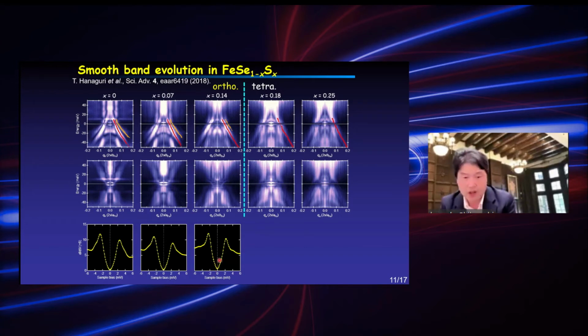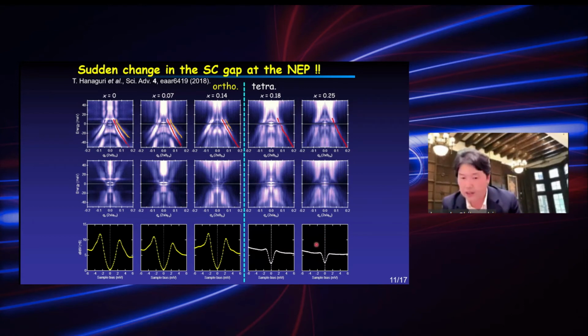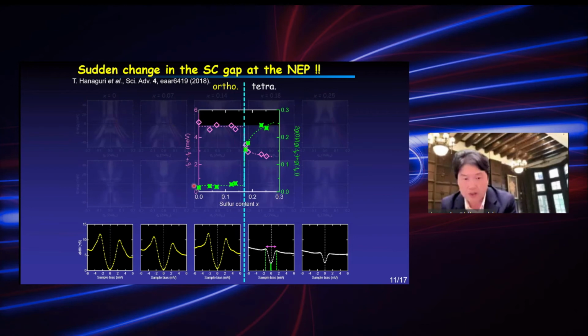However, if you go into the tetragonal side, outside the nematic phase, we find a very large zero energy conductance. If you plot the zero bias conductance divided by the gap edge, shown by this green data, you can see it shows up immediately when going from orthorhombic to tetragonal side. So there is a big jump. Only in the tetragonal side do we have this very large zero energy dI/dV.